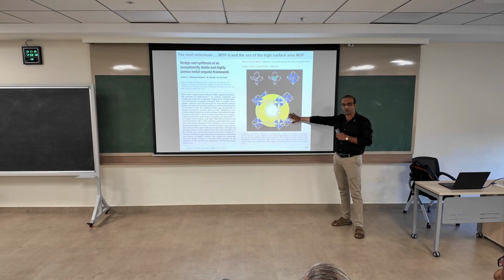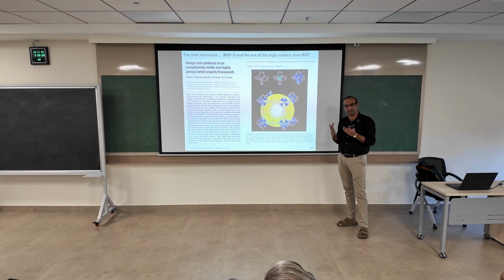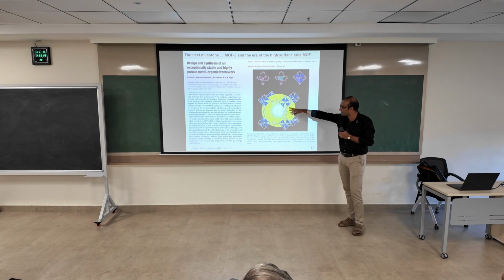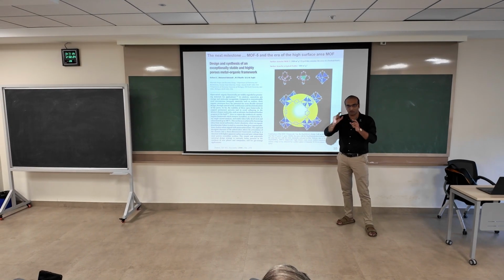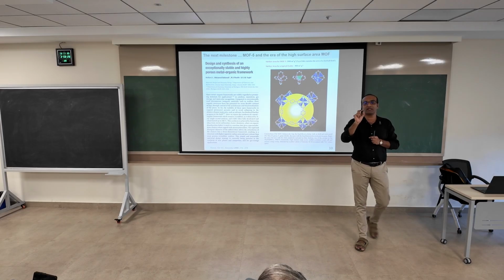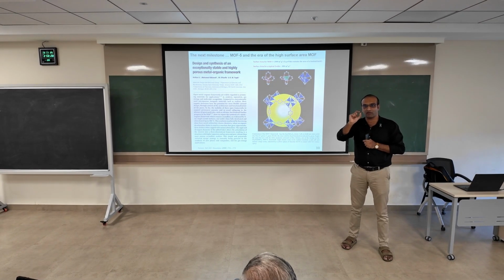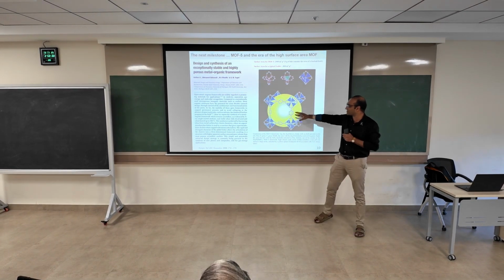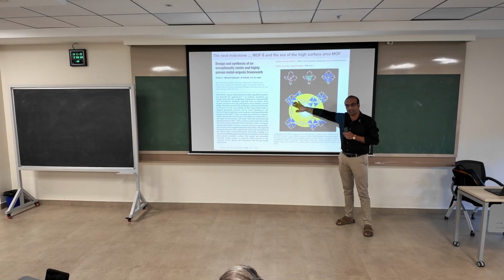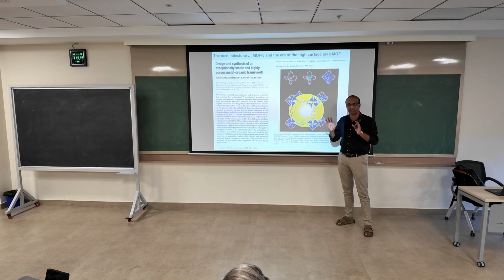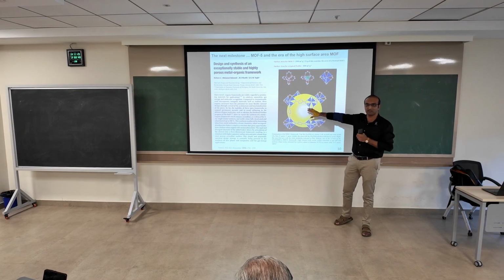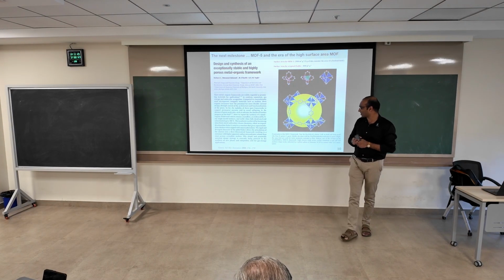Okay, the thing about all these metal organic frameworks was actually finding what combination of linker, this is called the linker, and node, the zinc oxide node, to use. Earlier, when Robson made it, it was just a single metal ion, but in the case of this MOF-5, it was a zinc oxide cluster. Typically most MOFs now, the most robust MOFs, will use some kind of zinc oxide cluster, and there'll be a lot of coordination chemistry involved in them coordinating with the organic linker, and the strength of that bond is what determines the integrity of the MOF.